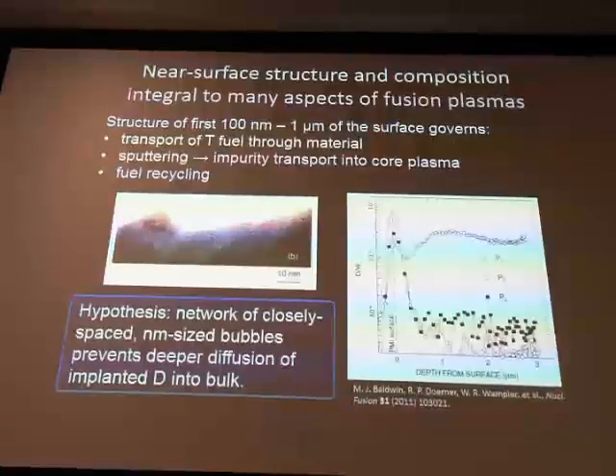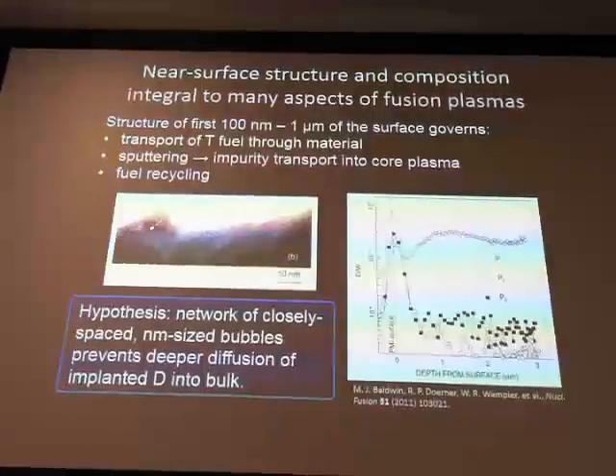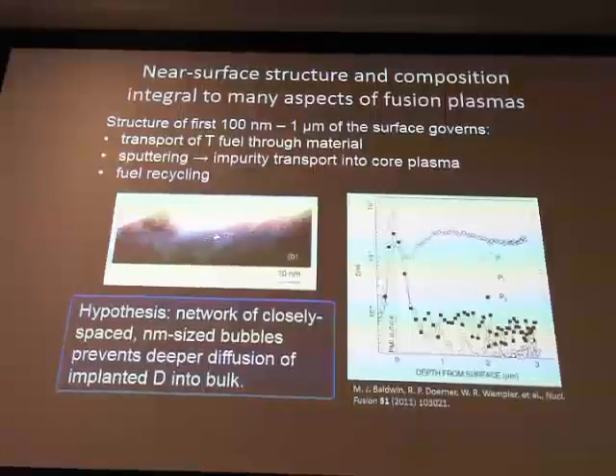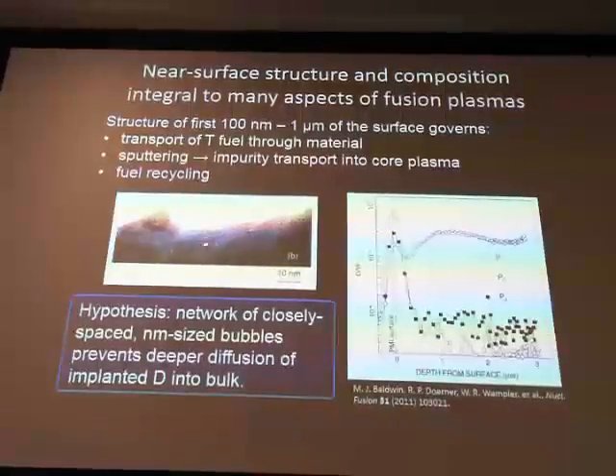What's becoming clear then is that the structure of the material in the near surface is really critical. This is a rather low resolution TEM image of the near surface region after exposure to a combined helium-deuterium plasma, and you can see the small white dots in this image correspond to small helium bubbles near the surface. It's thought that a network of closely spaced nanometer-sized helium bubbles is responsible for trapping of deuterium, promotes release during the implantation process, and prevents deeper diffusion of deuterium into the bulk.